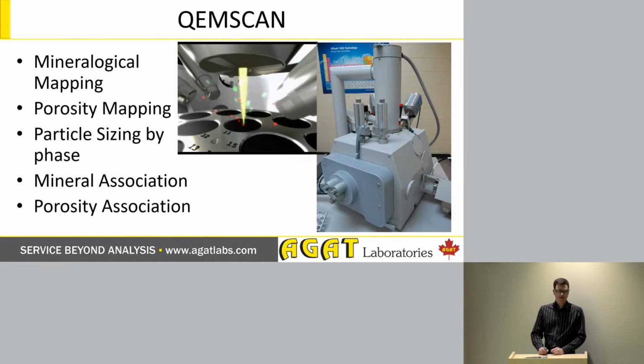QEMSCAN is a similar technology to scanning electron microscopy, but it takes it a step further, adding the ability to map and model the mineral distribution across a region of a slide. Or, in the case of disaggregated or particulate samples, we can mount them in epoxy and actually zap them to see which grains are which all the way through. So it provides some of the similar results of a thin section and an XRD, but from one tool. It can also provide us the particle sizing, so you can take all the particles and produce a particle size distribution, or you can even do that by mineral phase.